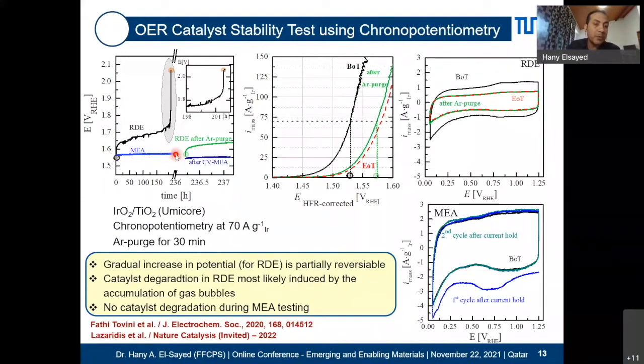Same thing. You stop, you do something similar to argon purging in MEA, and then the line is still the same. So it goes just straight. So there's no potential increase.